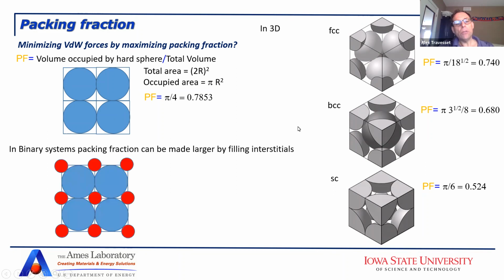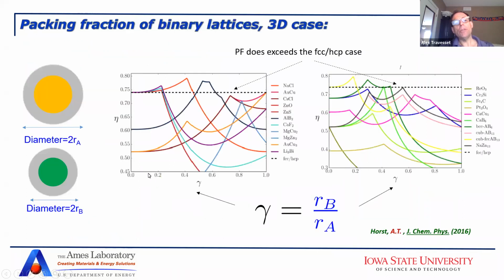We are interested in binary systems. In binary systems, we have 2 types of spheres. And then you can see that you can improve on the packing fraction by filling the interstitials with the smaller spheres, and that would give you a packing fraction that is larger. But in general, this packing fraction will be a function only of the ratio of the 2 radii. So when you plot the 3-dimensional case, what you get is a curve that, depending on the ratio of the 2 sizes, will give you packing fractions that look like that. Some lattices will improve on the packing fraction of single component FCC, which is the maximum packing fraction that you can have with just one type of particle.